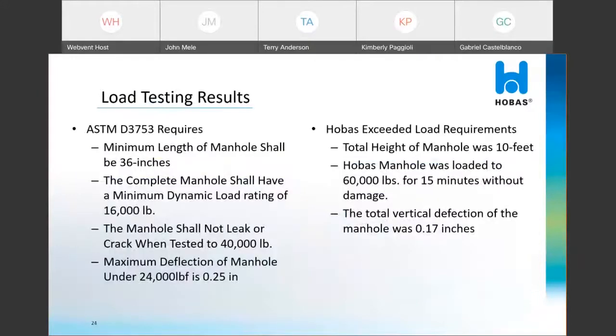The load test was a tremendous success. The standard has several requirements for performance. At 24,000 pounds of load, the vertical deflection shall be less than 0.25 inches. In our test, the deflection was about 2/3 of that, or 0.17 inches.